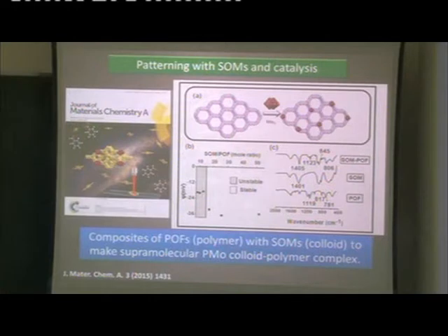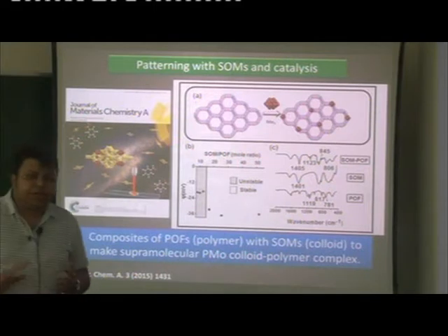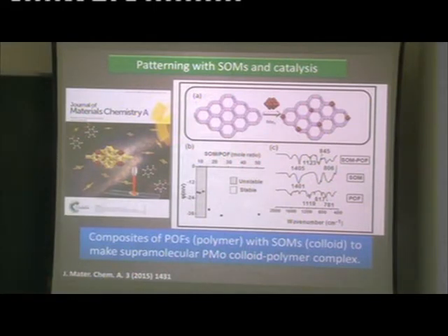So as an experimentalist, how do you find out whether you have stabilization or not? It is by measuring the potential, that is the zeta potential. It gives you a measure of the charge on the surface of your particles, which you can find out by concomitant laser light scattering, right? So this is how we were able to find the zeta potential. And this zeta potential has a certain window within which you have stabilization. If you cross that window, you have destabilization or instabilities.